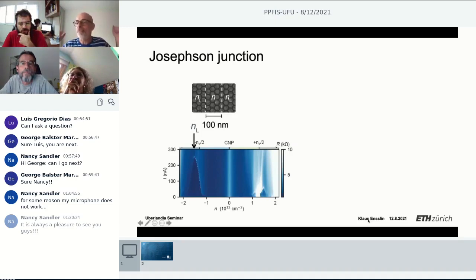Now you would say, of course, get rid of the graphite backgate. But yes, if we get rid of the graphite backgate, we cannot tune our dot anymore, because we need an electrode from top to bottom. We need this displacement field to get the confinement right. Okay, so all of that can be solved. We just need now to make a gate which is exactly the size of the dot and stops at the edge of the dot so that the line is not shorted.